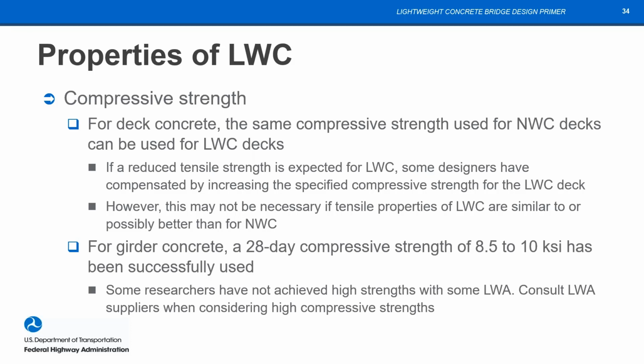Also, that's for decks. We can easily achieve typical deck concrete strengths. For girders, you can probably get up into the 8.5 KSI, and some aggregates can get up to the 10 KSI range. And that's something that has been shown in a number of different projects.